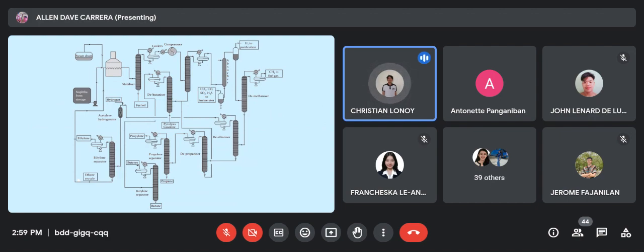Para mapigilan po ang pagkakaroon ng coke, ang naphtha feed ay pinapadaan sa heater tube at a very high speed. Products from the cracking furnace, yun pong kulay gray po na may parang bahay na may chimney sa taas. Yun po yung cracking furnace are quenched by hot oil and cooled before they are sent to the separation units. The product mixture then flows through a series of separators. Included po dito ang demethanizer, which liquefied gases are separated from methane. Sa deethanizer, it separates ethane and ethylene mixture from liquefied gases containing propane, propylene, butane, butylenes, and etc. Pati po sa depropanizer, liquefied gas mixtures from propane and propylene. And the debutanizer, butane, butenes, and butadiene are recovered as the top product and heavier are recovered as the pyrolysis gasoline, or the bottom product. Lahat po yan ay multiplated distillation columns.